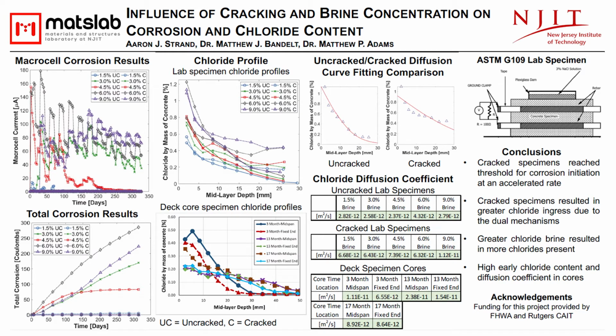For this project, the impact that brine concentration and the presence of a crack has on laboratory-based corrosion testing was looked at. The early results from this study were used as a companion and guidance on a larger scale model bridge deck specimen, which was subjected to freezing and thawing cycles, a moving load, and applied de-icing salts. For laboratory testing, ASTM G109 was used to monitor the macrocell corrosion that develops between the upper and lower reinforcement. Corrosion is stated to have initiated once the specified threshold has been met.